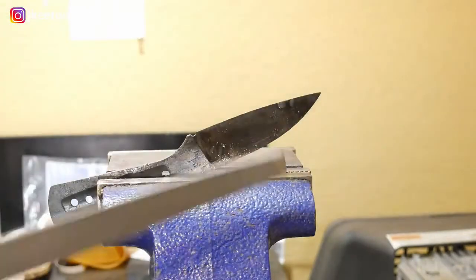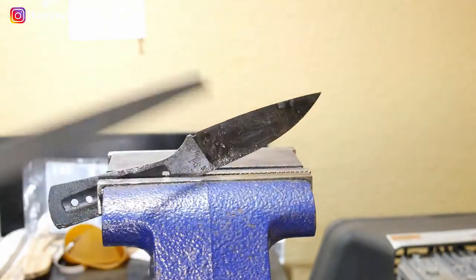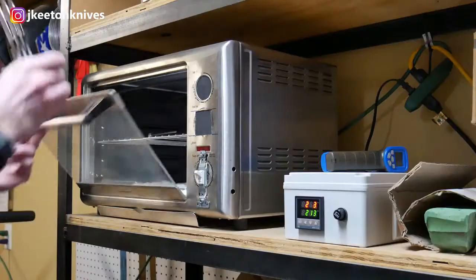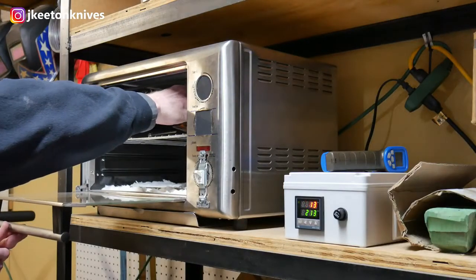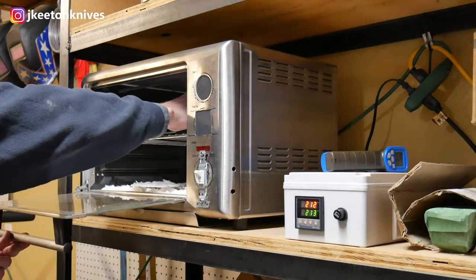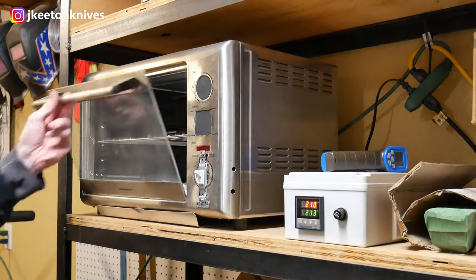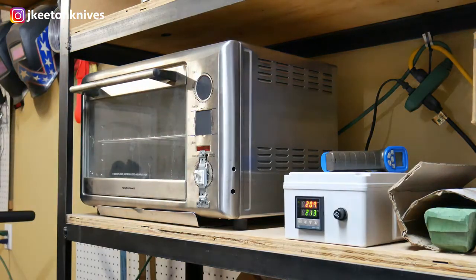So now we have a super hard blade. It file tested easily. We're going to move on to our first tempering cycle at 213 degrees Celsius. I did pick up a small warp during the quench, and we're going to mess with that in our second tempering cycle so as we don't risk snapping this blade.